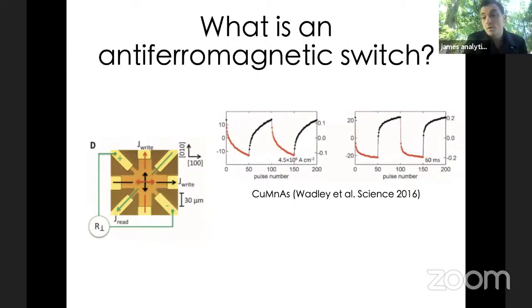So this is what a typical signal looks like. You will pulse current in the red direction, so that's the north-south direction, and you'll see resistance changes getting closer and closer to a lower and lower resistance state. Then you apply in the black direction, and you'll apply multiple pulses in that direction, and it'll go to a higher and higher resistance state, and so on. And applying a higher current again, you can kind of get to what looks like a saturated value after many pulses. But this kind of sawtooth-like structure is quite typical of these kinds of systems.